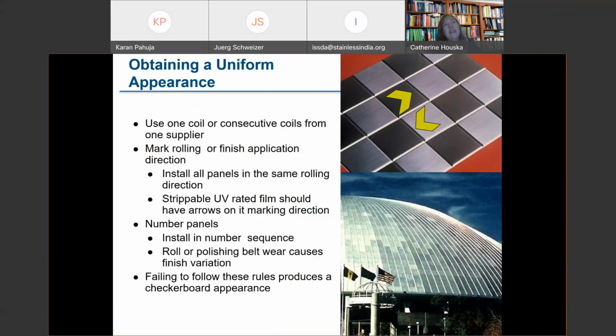To obtain a uniform finish, it's important to ideally use one coil or consecutive coils from one supplier. That doesn't always happen. In the appliance industry, there can be multiple suppliers getting stainless steel from different places. And in that case, they are very careful about making sure the finishing steps are the same and have very careful surface roughness and other tolerance ranges.